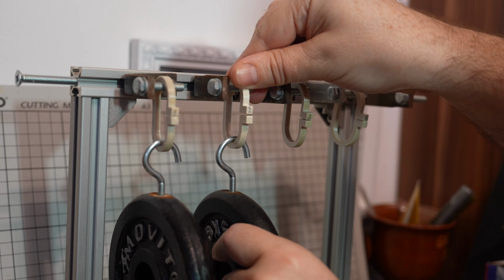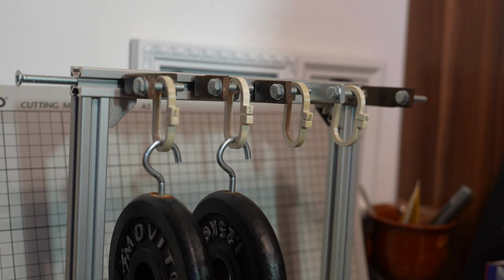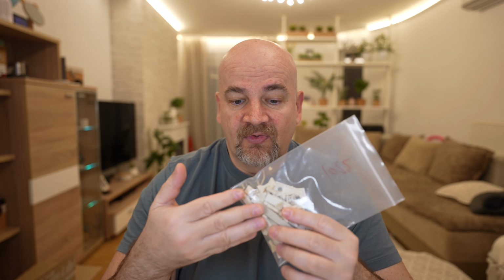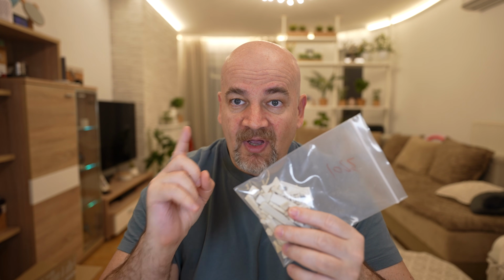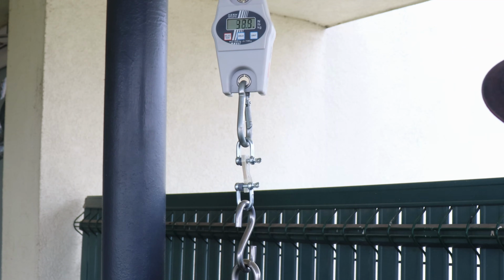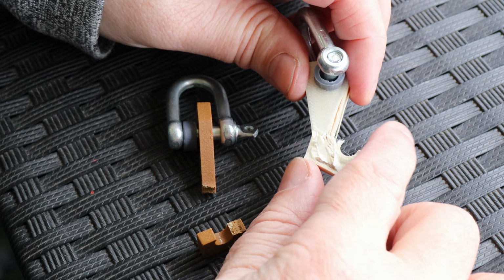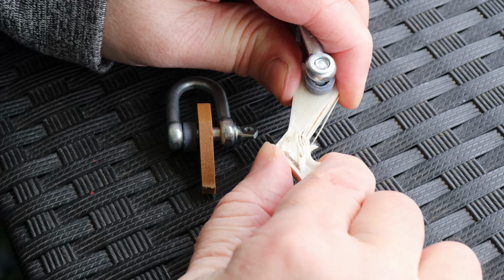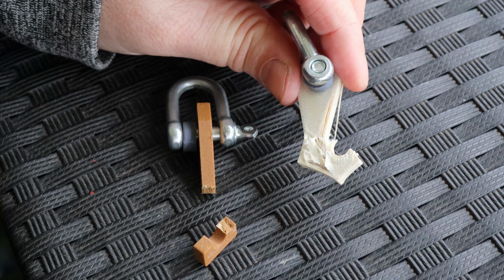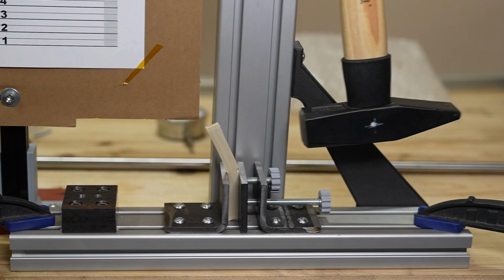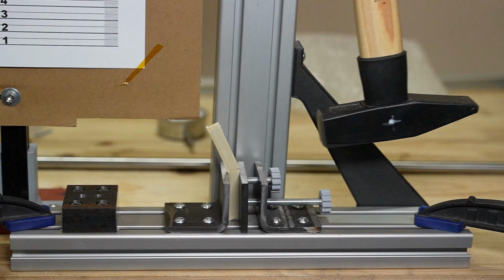I really have mixed feelings about this filament. On one side they created something new, very unique, extremely strong in X and Y direction, until that weakness of the layer and wall adhesion is involved. This means we need very specific applications for this filament. But I believe it would be much stronger if it would have good layer adhesion. For example, in my hook test, it is strong even now, but it could be much better if it would have good wall adhesion. Or in my impact test, that object wouldn't even bend if it would have good layer adhesion.